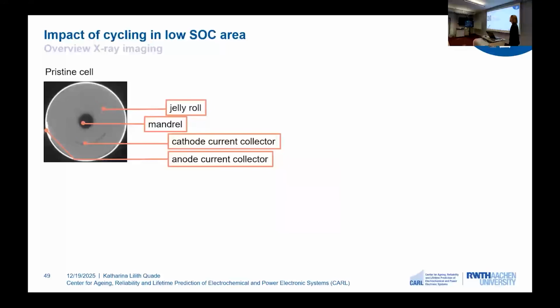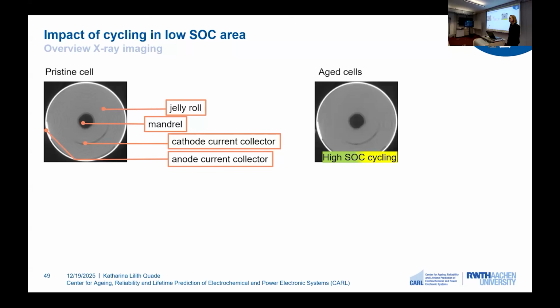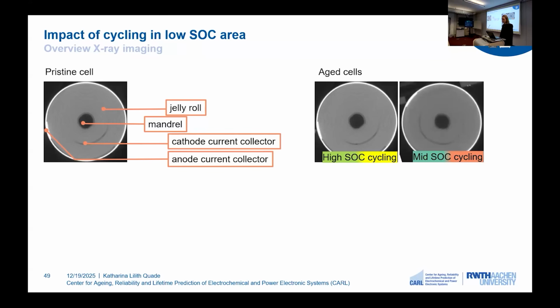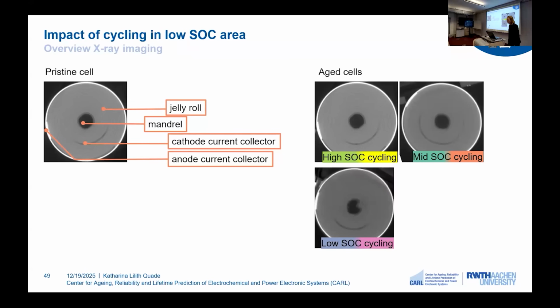And to analyze this further, we took CT images. So here you can see a CT image of our pristine cells, so a cross section. We can see the jelly roll, we can see a mandrel in the middle without a supporting structure, and we can also see the cathode current collector as well as the anode current collector. And now we also took CT images of the cells in the aged states across different categories. And here you can see some exemplary cells for the different categories. So here you can see the high SOC cycling, for mid-SOC cycling, and here for low SOC cycling.